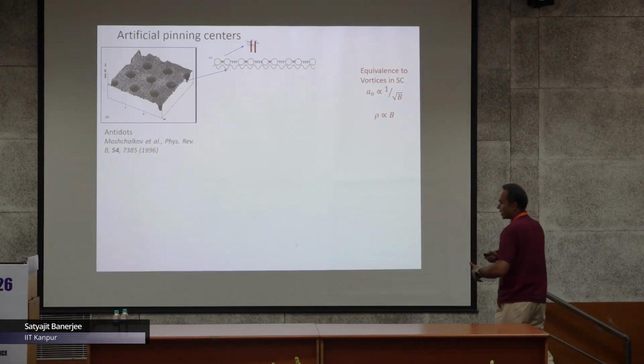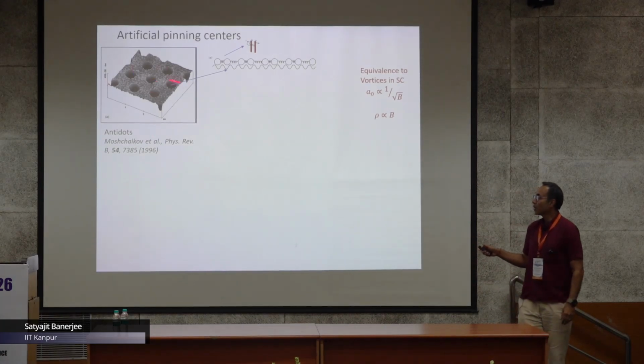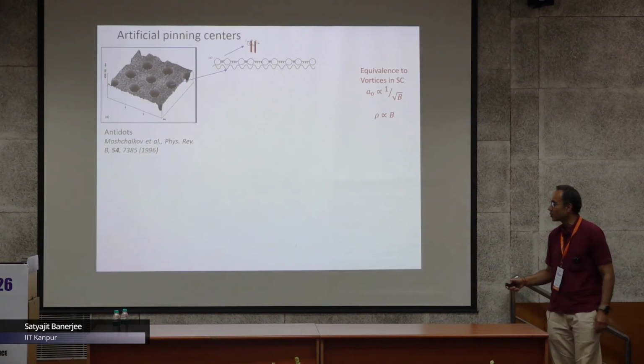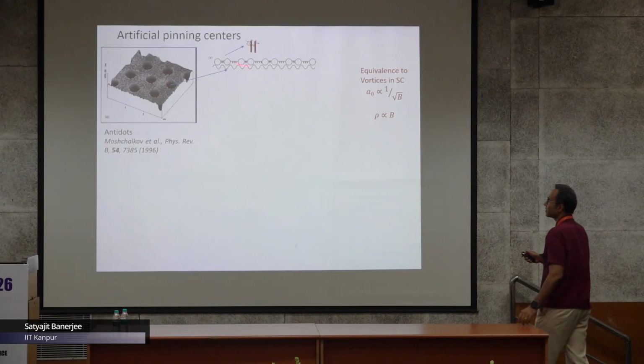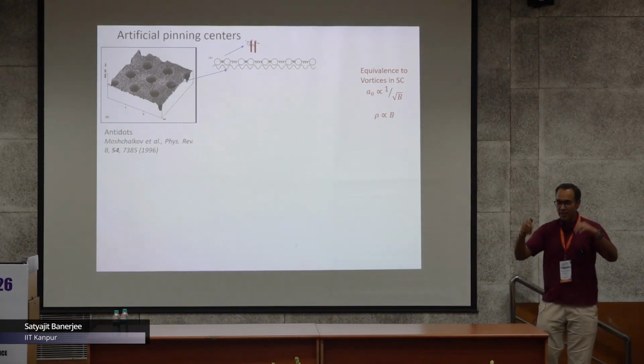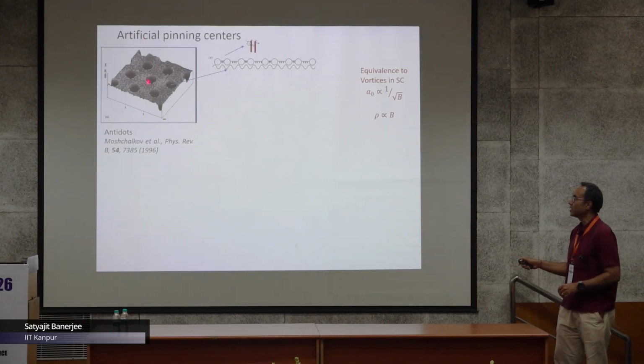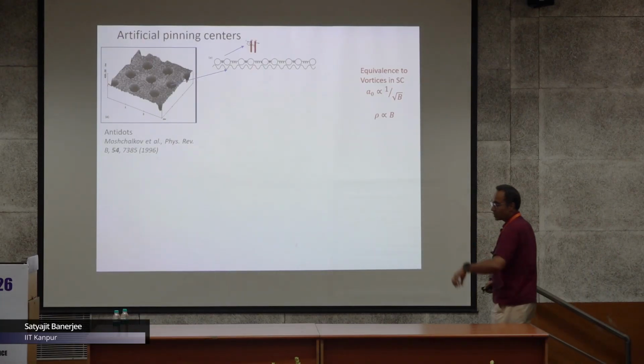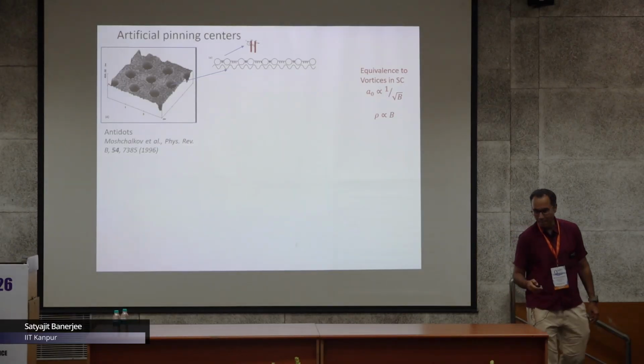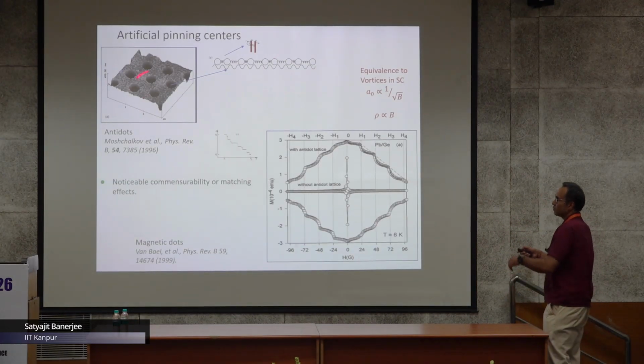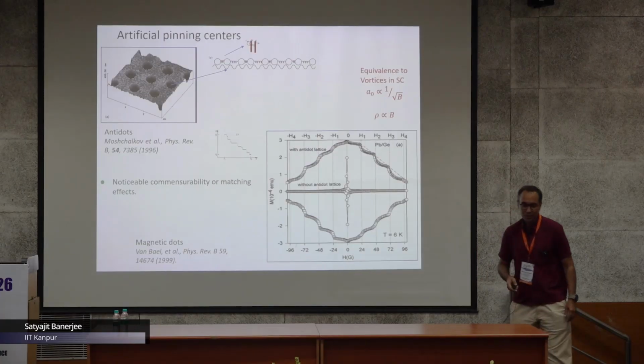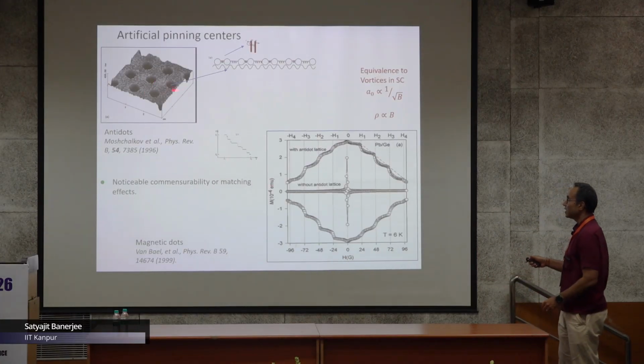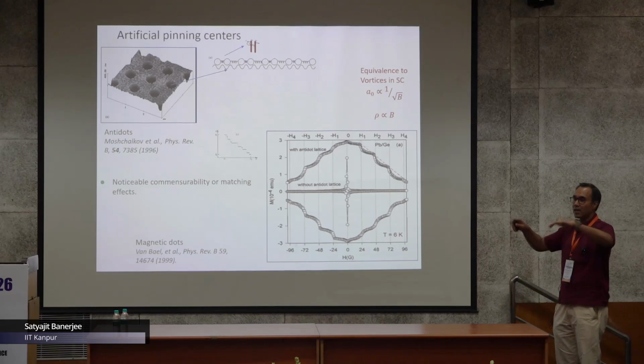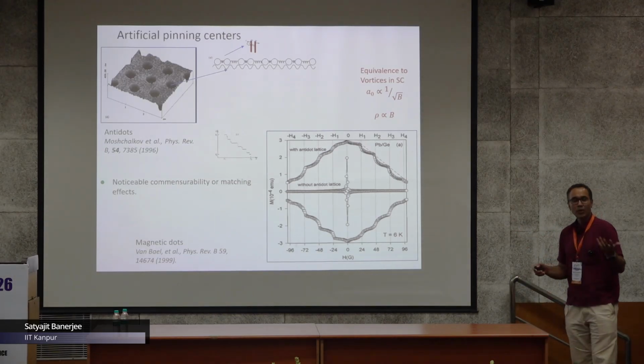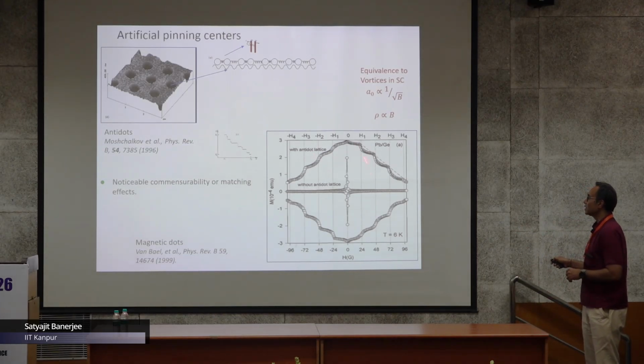These periodic defects lead to commensurate states where vortices start matching with the holes created inside the superconductor. This work started around 1996 or so. Whenever there's a matching of vortices with the underlying periodic potential, various measured quantities of the superconductor show jumps, breaks in curvature.